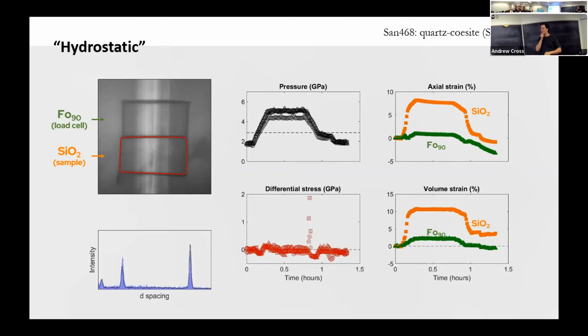This was the first experiment we did, and we figured out pretty early on that this permanent volume loss just corresponds to some small amount of porosity in the sample to start with that packs down as we're increasing pressure. So that's why the sample is slightly smaller at the end of the experiment. Every experiment that we've done since this one, we've done a pressure cycle at room temperature to begin with. So we're not transforming the sample, we're just packing all the grains together to get rid of that porosity. And then we end up back at a starting volume.